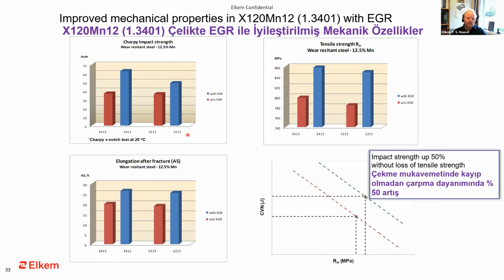So we actually see here that we get both increased tensile yield strength and tensile strength, but we also improve the ductility and the toughness of the material. And that's quite rare when you work with steels. Usually you have to choose better strength or better toughness, but here we actually get both, which is in line with theory, of course.